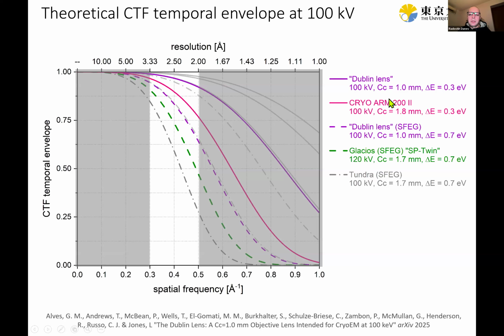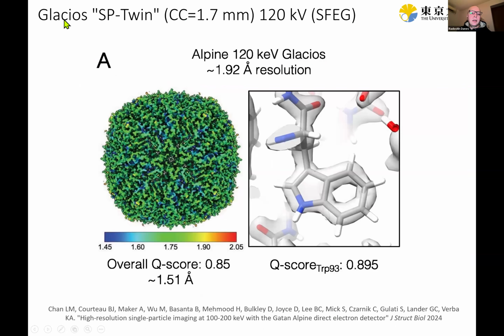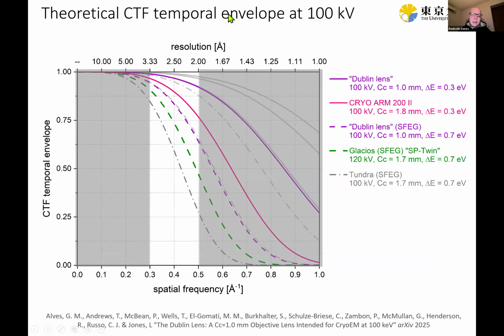Now the CRYO ARM 200 with the narrow gap pole piece already starts to hit a bit below 2.5 angstrom, and then the other machines like the Glacios with the narrow gap. I forgot to mention the Gabe Lander dataset here was collected on a Glacios with a narrow gap objective lens. So it's a 1.7 millimeter with the Schottky FEG though, so it's not a cold FEG like the CRYO ARM. And then we have the Dublin lens with the Schottky FEG, shown here in purple. And on the bottom here is the Tundra, which is a standard product. It is with a narrow gap, but it has a Schottky FEG source.